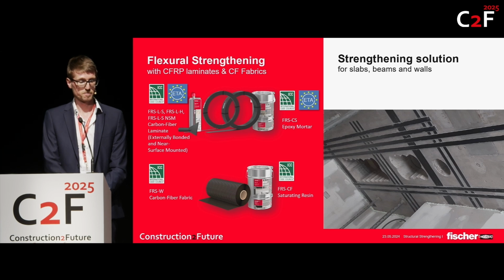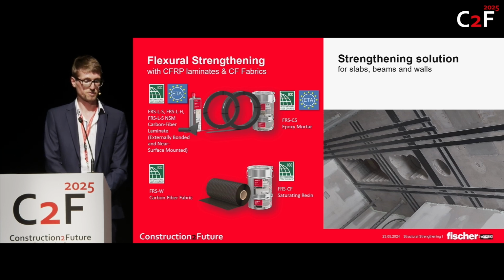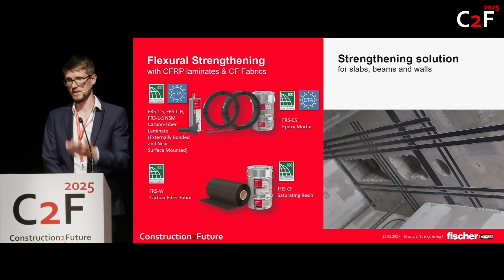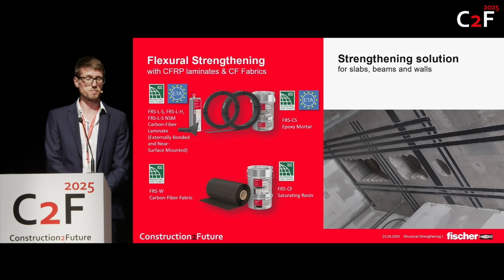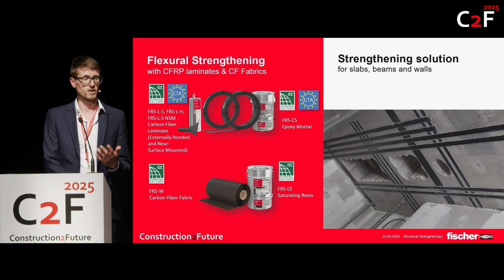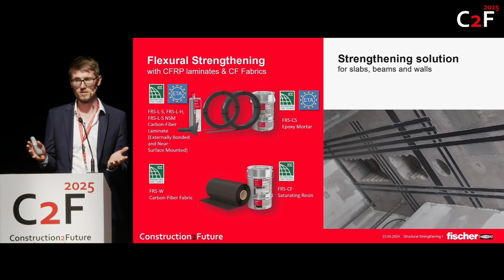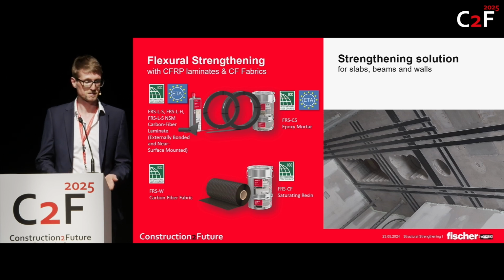So it's an R4 repair mortar that can be well used for retrofitting projects, because in many applications you don't just have a structure that is deficient in terms of lacking reinforcement, but also you will have concrete spalling or something else that you may repair. You may need to reprofile a cross-section, and if you do that with a normal cementitious repair mortar, of course you're cheaper, but you'll have to wait 28 days until you can load the structure. If you want to do it in 2 days, you use an epoxy mortar and you're very fast.